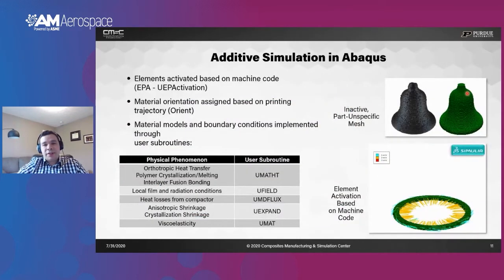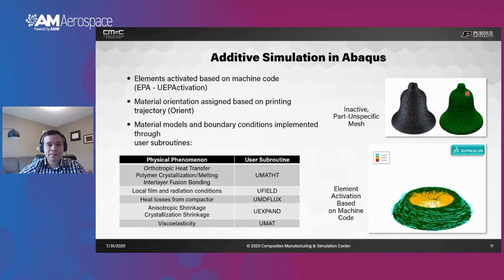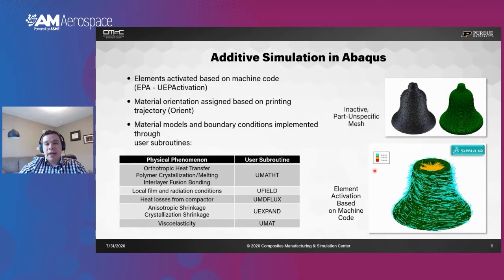So in terms of the technology that is behind the simulation workflow, our primary tooling here is Abaqus from the Simulia brand, from Dassault Systèmes. We basically use the machine code output by the slicer and transform it into what we call an event series to activate elements in a finite element mesh. And we capture multiple phenomena that develop simultaneously during the printing process, including anisotropic heat transfer, polymer crystallization and melting in the case of semi-crystalline polymers, and interlayer bonding. We even capture local convection coefficients or conditions that develop inside the different printers.